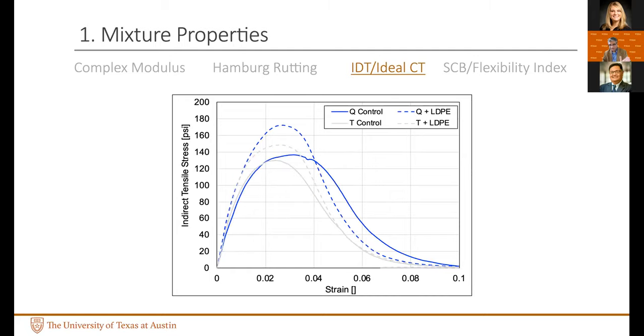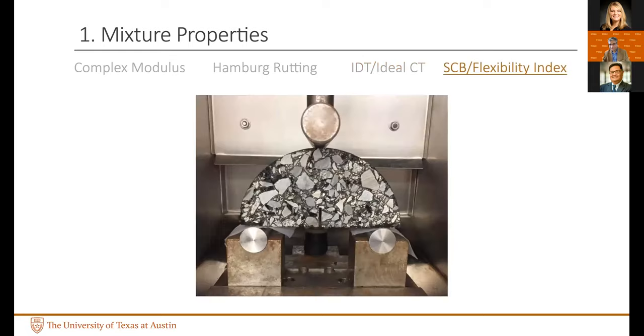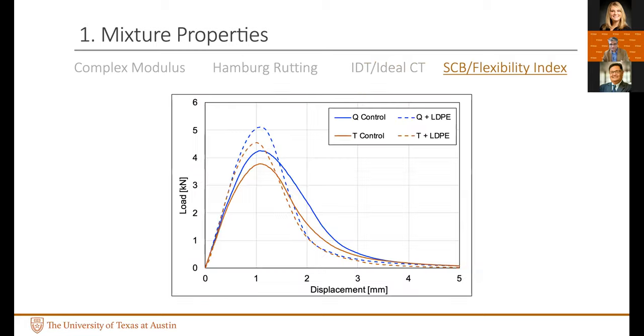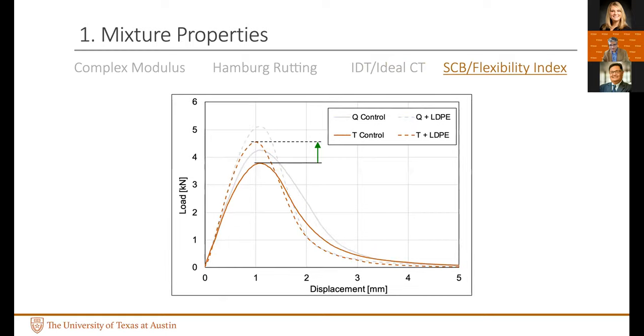And if you look at the other mix, also the same behavior, see an increase in strength, a little bit loss in ductility. We did the same thing with the SCB flexibility index, and you would see the same kind of result. You see an increase in strength, a little bit loss in ductility. So this is consistent across the two binders, across these two different tests and so forth. So you're beginning to see this pattern here that there is a little bit of compromise when you're using these plastics.